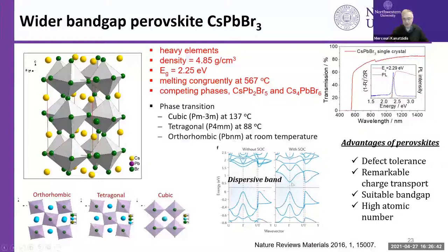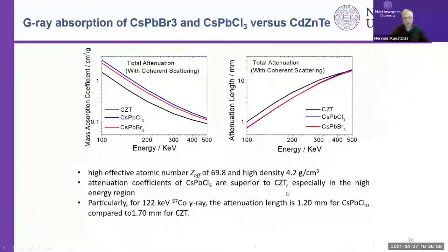Its electronic structure is excellent. You see here, this is a calculation. This is the valence band. This is the conduction band. It's a direct gap, and they have very nicely dispersed electronic bands, which is good for electron and hole mobility. So this material is defect tolerant. This is how it compares. This is the mass absorption coefficient as a function of energy, and the red line is what we're looking at. In this energy range, it's better than CZT.